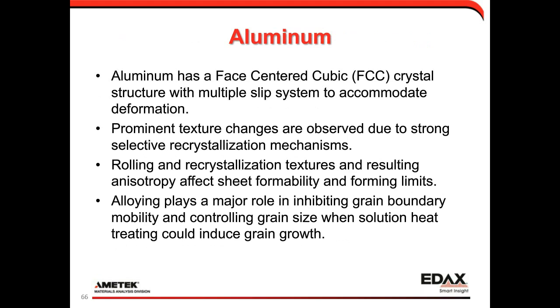And then just to summarize for aluminum, aluminum is face-centered cubic, has multiple slip systems, and is a little bit easier to deform. But you can get prominent texture changes in aluminum due to strong selective recrystallization. As you deform material and heat it up, certain orientations will recrystallize and grow. These rolling and recrystallization textures will affect your sheet formability and forming limits. And alloying aluminums will play a major role in inhibiting grain boundary mobility and controlling grain size when heat treating your materials.